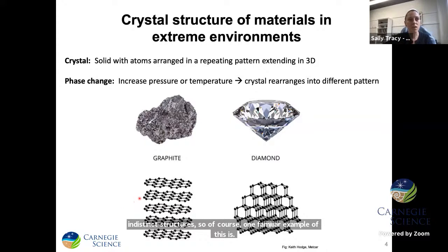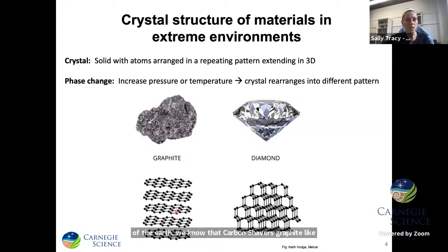carbon, where on the surface of the Earth, we know that carbon favors a graphite-like structure, which is composed of sheets of carbon atoms. And these sheets cleave off in planes readily from one another, making graphite a soft and flaky material. However, when we subject graphite to the intense pressure temperature conditions found deep in the Earth, these sheets of carbon will tend to reorganize themselves into what we know as the diamond structure, which is a tightly bonded 3-dimensional network that has very, very different physical properties than graphite, being the hardest known material.